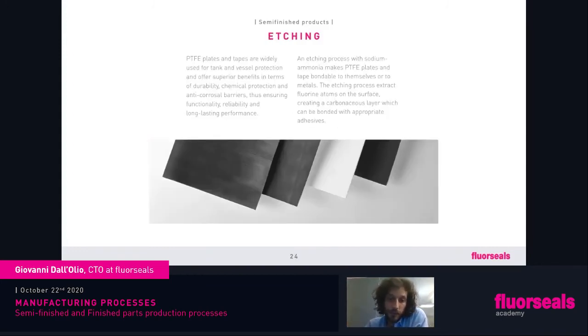After this skiving, another post-processing that can be done on PTFE is called etching. Etching is the only known way to make PTFE gluable. What does it mean? PTFE has a certain surface energy that doesn't allow anything to attack its structure and to glue to the PTFE. But using this etching, that can be sodium ammonia etching or sodium naphthalene etching, we can remove a fluorine layer from PTFE. And as you can see, the PTFE will become black because the carbon of the molecular structure of PTFE will be shown. The carbon is able to make bonds with other things like glues.